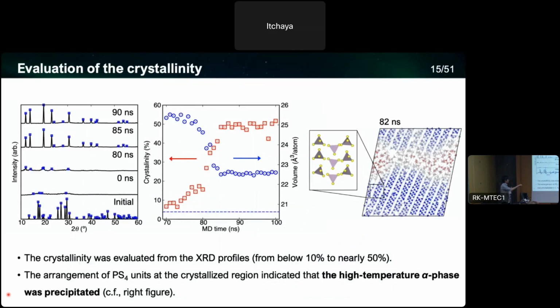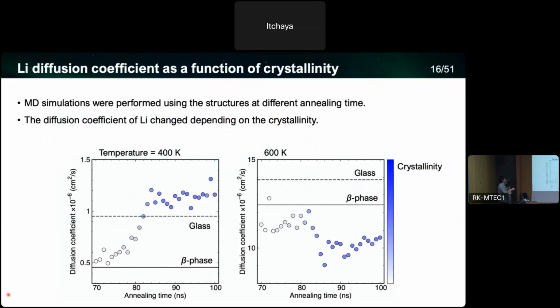Sorry, I'll go back. As we can see, we have models with different crystallinity, so we can investigate the ionic behavior at different crystallinity. That is this slide. For each structure with different crystallinity, we performed additional molecular dynamics simulations to get the diffusion coefficient of lithium. This graph is the case when we set the temperature to 400 Kelvin. The horizontal axis is the annealing time, which corresponds to the crystallinity. If you go right, the crystallinity increases, which is colored by blue. So a blue point is more crystallized, and a white point is close to the glass. As you can see, the diffusion coefficient changes as the crystallinity increases.